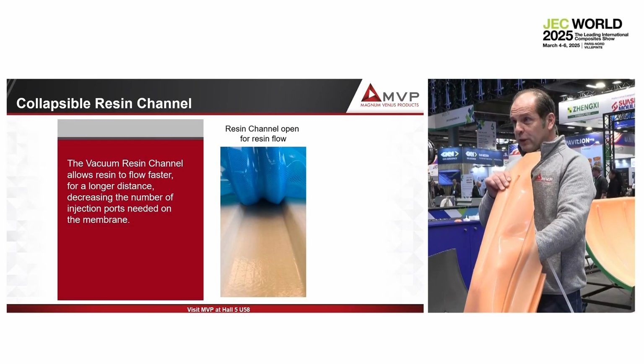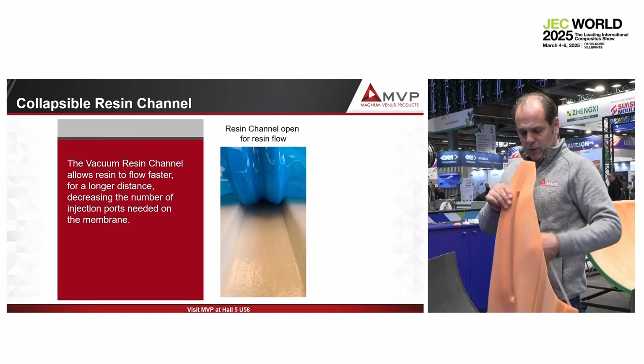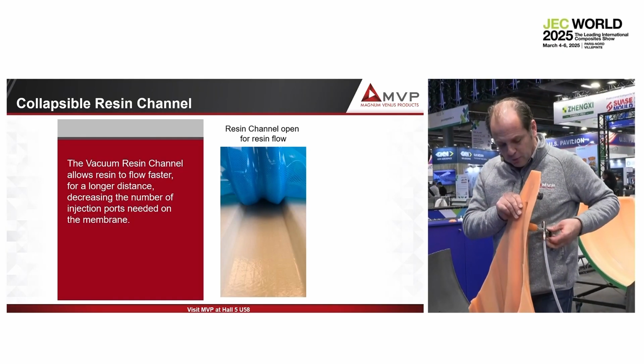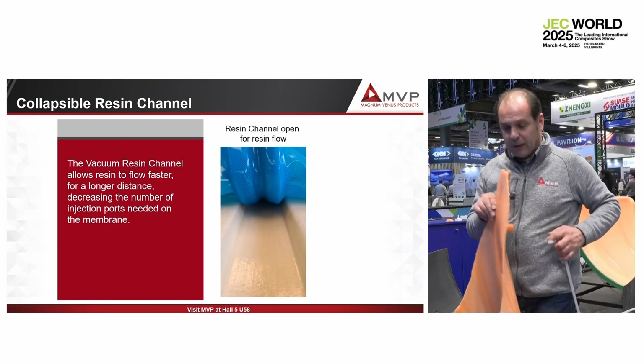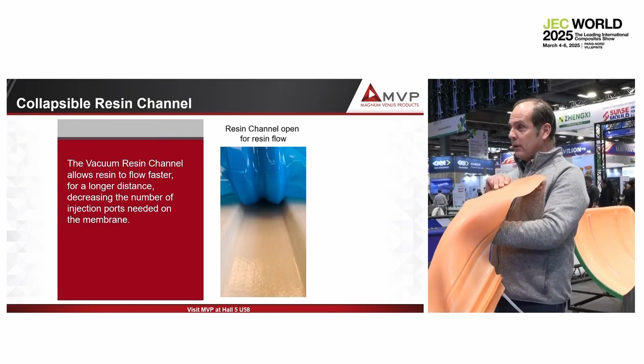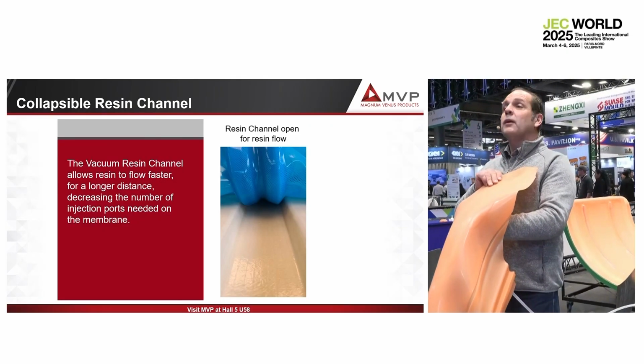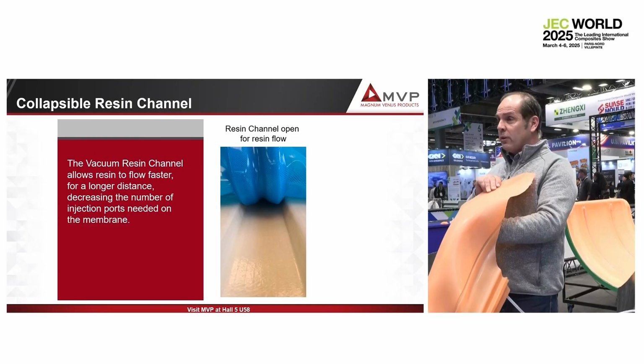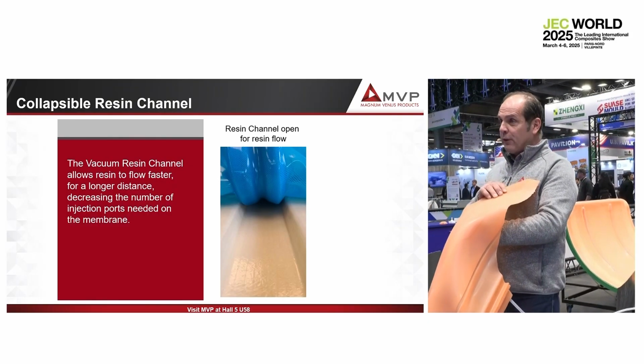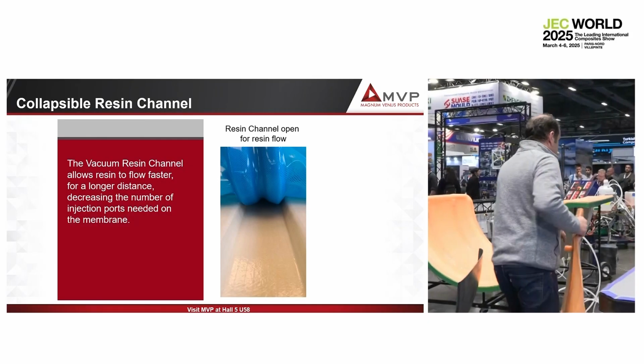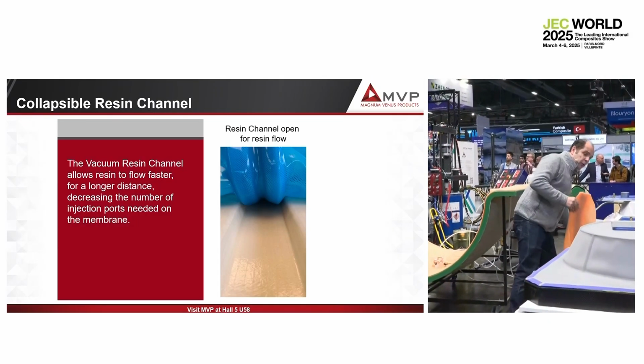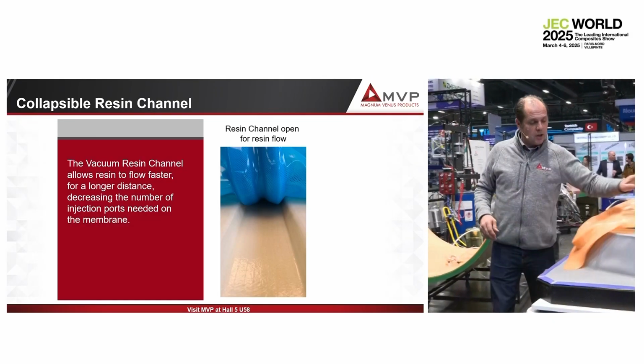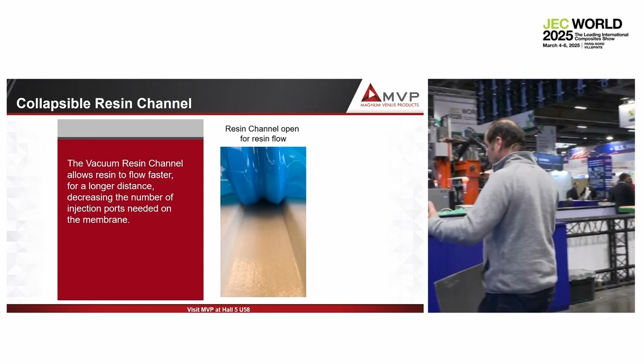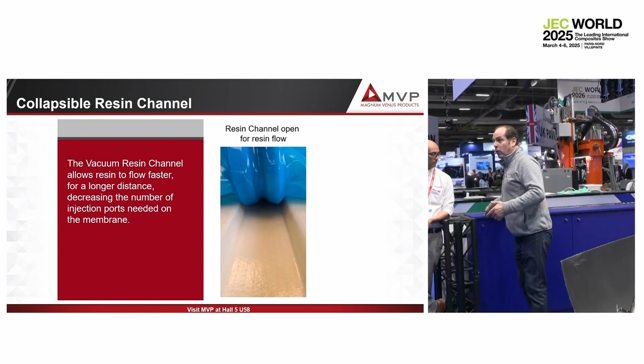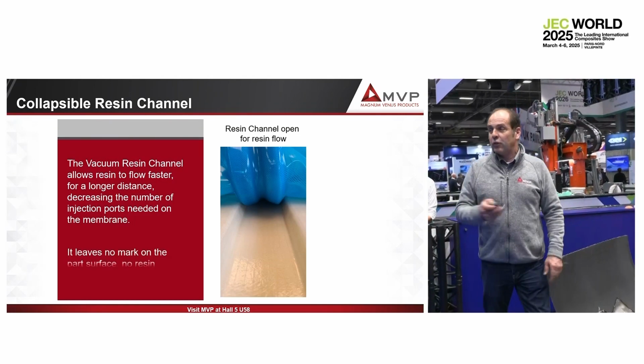As soon as we finish injecting the part, and even a little bit before, we stop pulling vacuum, and the membrane comes back to its original position. There is no resin waste. There is no excess of resin, no resin print-through on the part surface. Because of that, we can put as many resin channels as we like to decrease the distance of the resin flow, and then decrease the injection time.